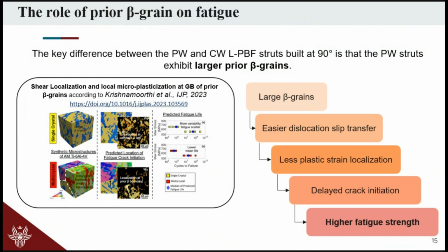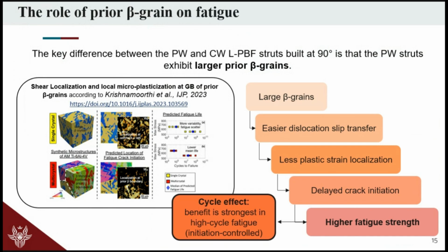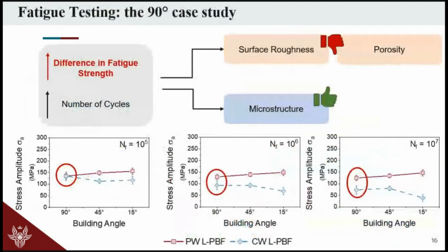However, the nice thing about this is that it's also cyclic dependent, in the sense that this benefit is stronger the higher the fatigue life is, because we are in an initiation control domain rather than in a bulk plasticity domain, in which instead the plastic strain localization tends to be widespread more over the overall cross-section. Given this, we basically can explain, indeed, not only the differences that we have in between the continuous and the pulsed wave laser powder bed fusion struts at 10^6 and 10^7 cycles, but also explain why at 10^5 cycles we have a sort of perfect match of the fatigue properties.